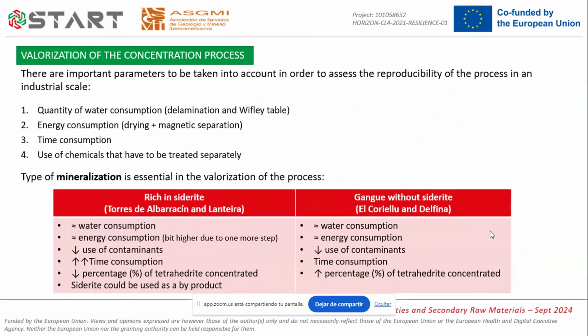With all the information, we are now making a valorization of the concentration process in the different cases that we have tested. There are important parameters to be taken into account in order to assess the reproducibility of the process on an industrial scale. And they are, for example, the quantity of water consumption during the delamination and the density separation in the Wilfley table, the energy consumption during the drying and the magnetic separation. The time consumption is also very important, and the use of chemicals that have to be treated separately.